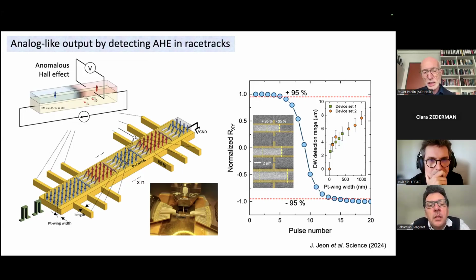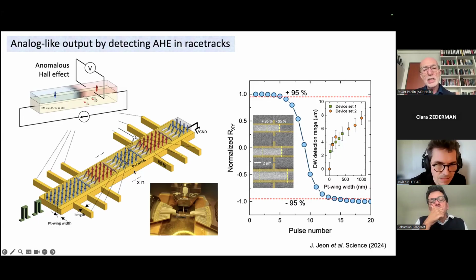This is actually a schematic cartoon to scale of a magnetic layer, which shows the blue and red regions, and the domain walls actually have a chiral Néel structure determined by the interface with the lower yellow layer, which here is platinum. And we build the platinum layer so that it is slightly wider than the magnetic layer. We call this a platinum wing.